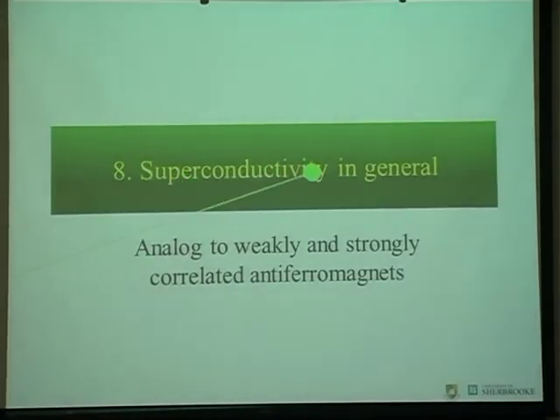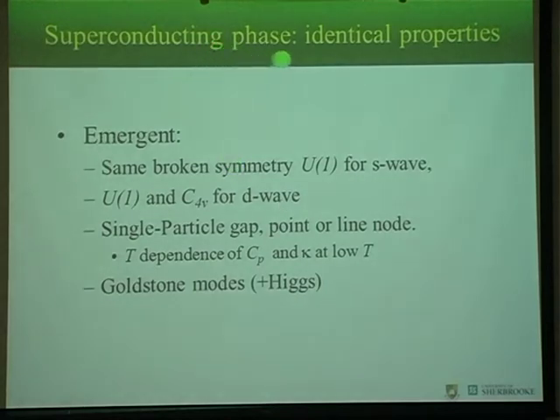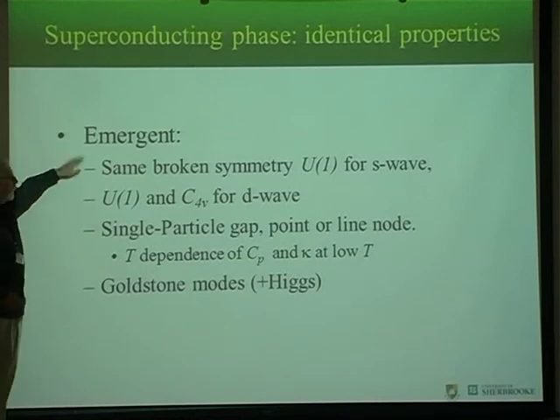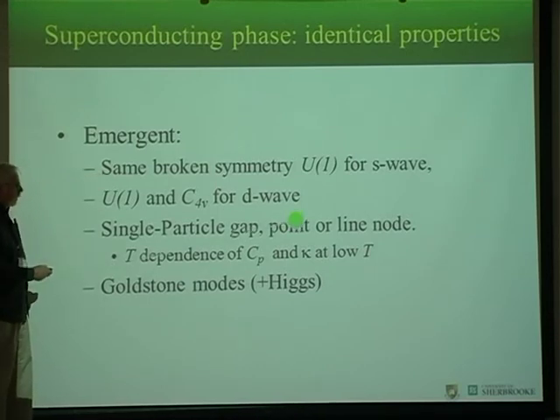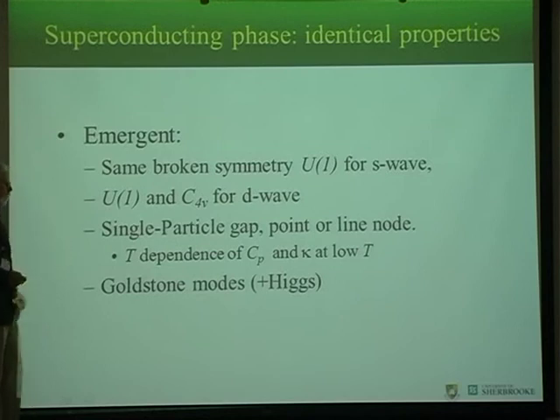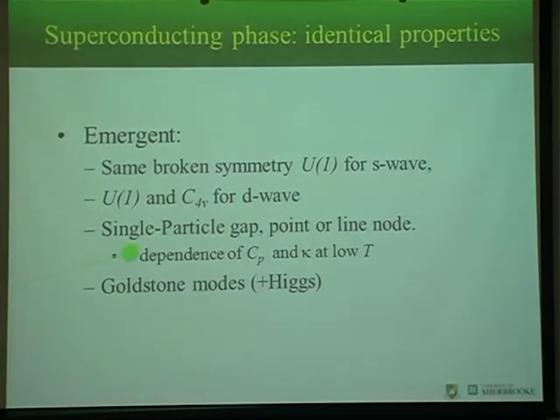Okay, I am finished now with superconductivity. And now some general statements first. There's a discussion to do which is similar to what I did between weakly and strongly correlated antiferromagnets. So in the case of the superconducting phase, there are properties that are the same, whether it's weakly or strongly correlated. So the emergent properties have the same broken symmetry. The broken symmetry is charge conservation, or U(1), for S wave. In the case of a D wave superconductor, you also break the rotation by 90 degrees. There's a single particle gap. And depending on the type of order, whether it's S wave or D wave, you have point or line nodes. And that will determine immediately the temperature dependence of the specific heat, the thermal conductivity, quantities like that at very low temperature. And also the Goldstone modes.